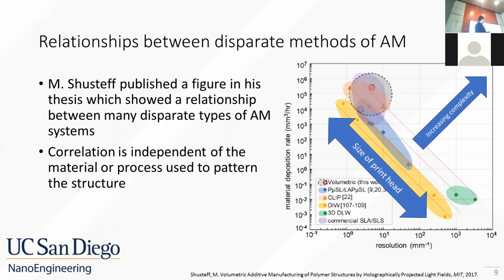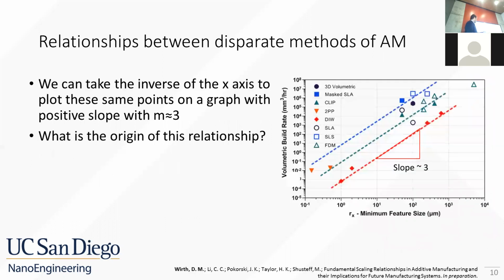And if you look into these individual data points, you'll see that you can move along the trend lines just by varying the size of the print head. And you can move diagonally by increasing the complexity of the system. In other words, increasing the number of simultaneous deposition paths or the speed at which these deposition paths are moving. So we can rearrange these same points on a plot of minimum feature size versus build rate to get a positive slope. And we see that this slope on a log-log plot is roughly 3.